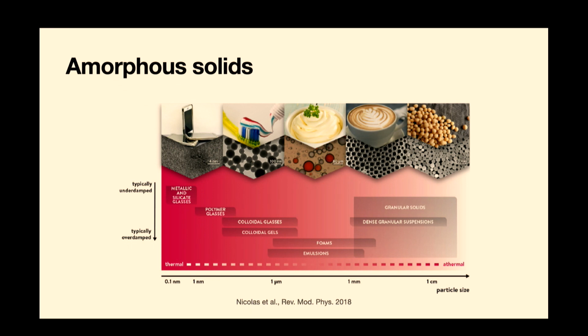So that's our setting, and as I've already said, these materials are out of equilibrium. The way they're structured depends on how they're made. These are not equilibrium structures. If you left them for a very, very long time, in principle, most of these things should crystallize, right? So certainly if they're sufficiently monodispersed that the particles are of equal size. Okay? So these are out of equilibrium structures. They're metastable, and they have a history-dependent structure that depends on preparation.